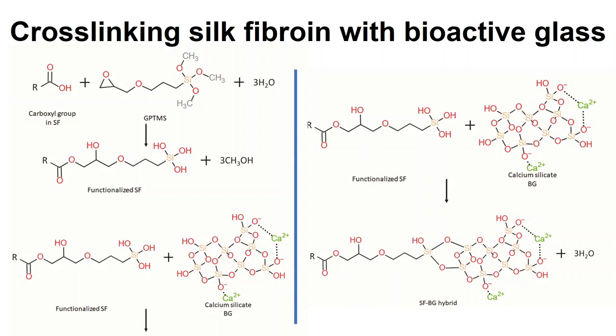And then we can allow them to undergo a condensation reaction between the calcium silicate network and this functionalized SF, silk fibroin. So finally, we got the hybrid, with the calcium silicate network forming an intimate connection with the silk fibroin. So this is the hybrid between organic and inorganic networks.